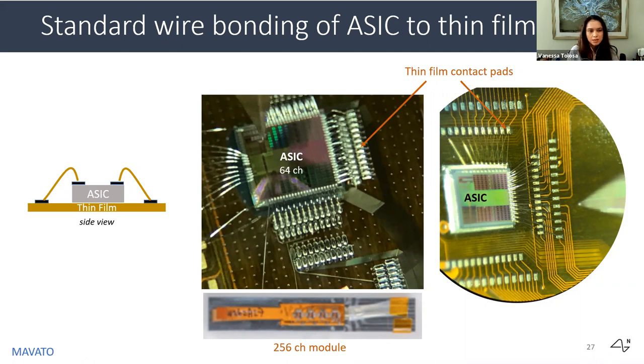So in most cases, at least that I've worked with, the thin film metal usually can't handle the bond energy and will delaminate during this process. So in this case, we electroplated nickel onto the pads to have more bulk to absorb that energy during wire bonding. And we got a much more reliable process.